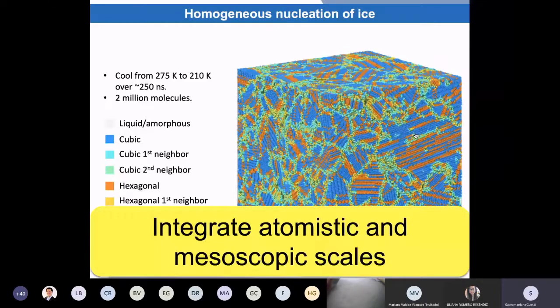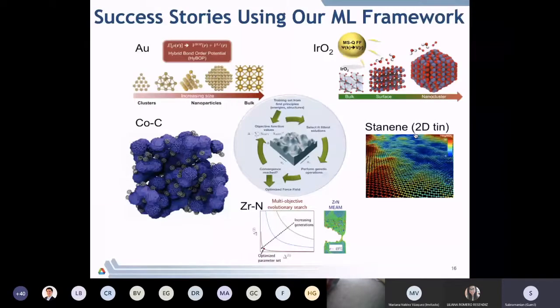So this is an example where we have integrated atomistic and mesoscopic scale, in the sense that we took the training data from the best available non-polarizable model and then supplemented it with experimental data where the model was actually found to be lacking, and we built a new model on top of that. That is not the only system we have looked at. We've looked at gold clusters, a metallic system. We've looked at iridium oxide, an oxide system for which there was no potential.